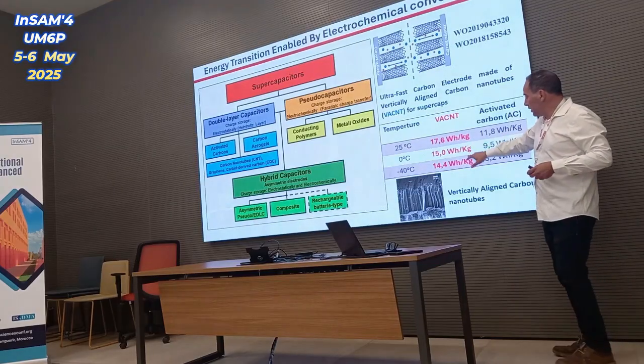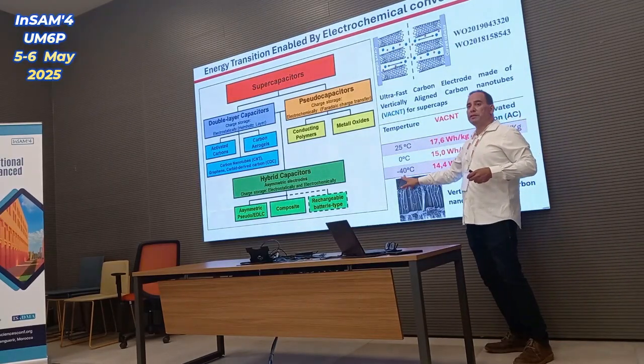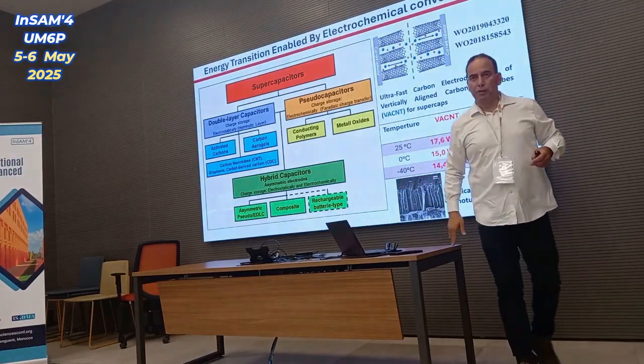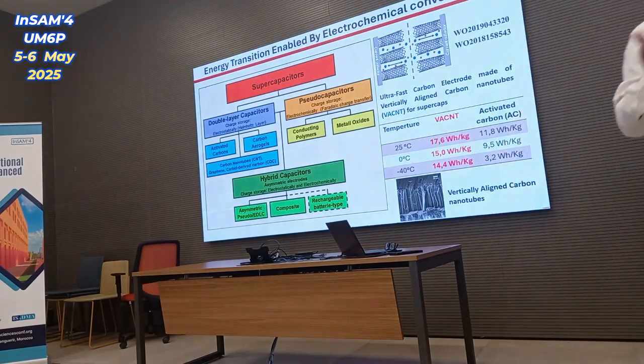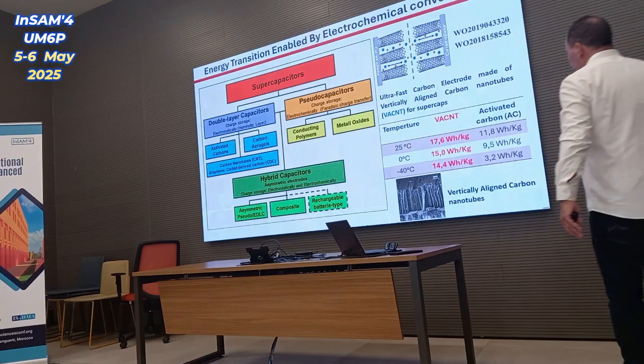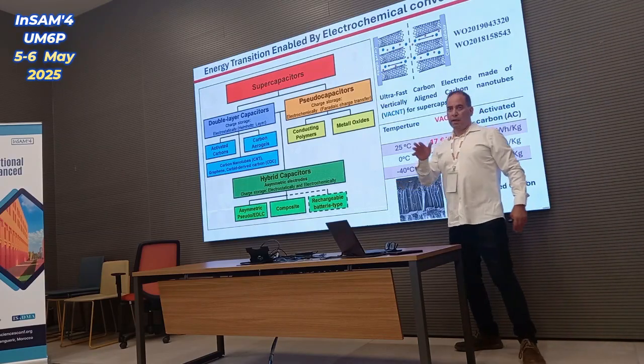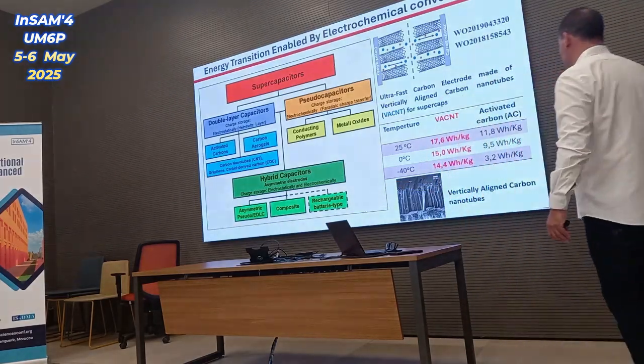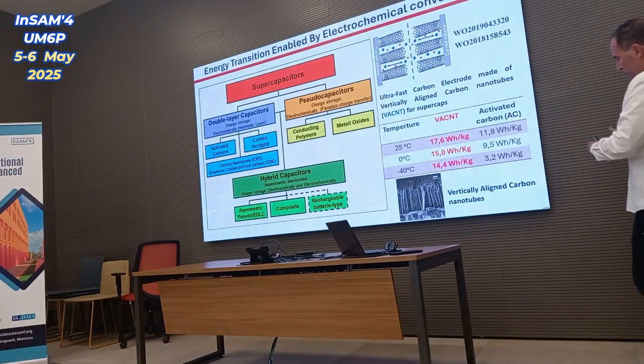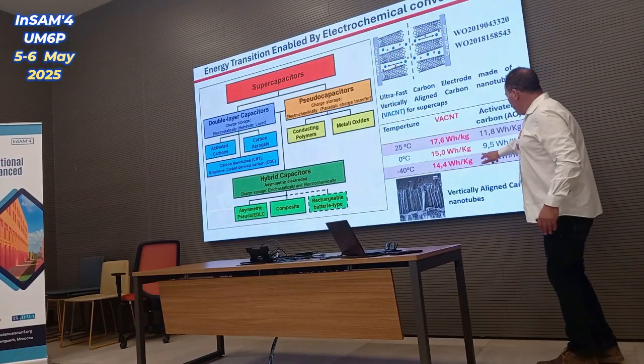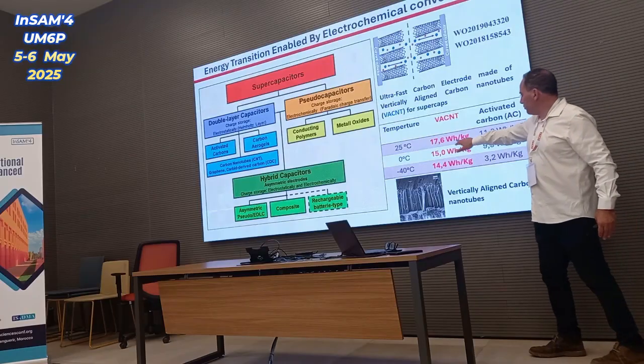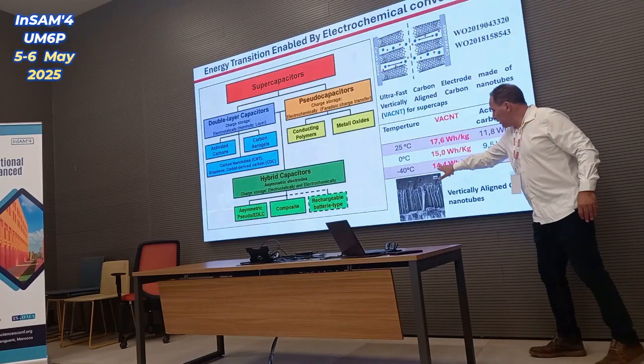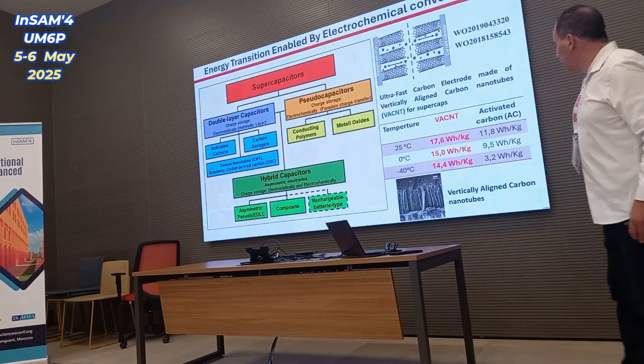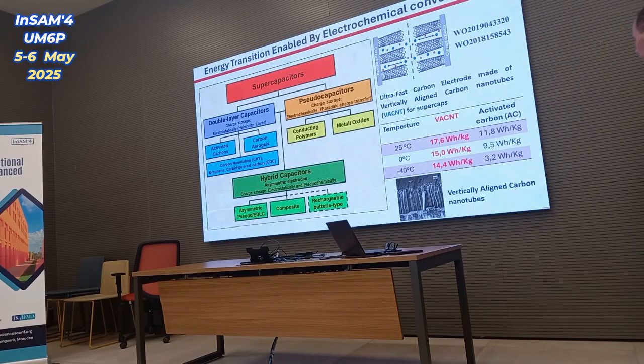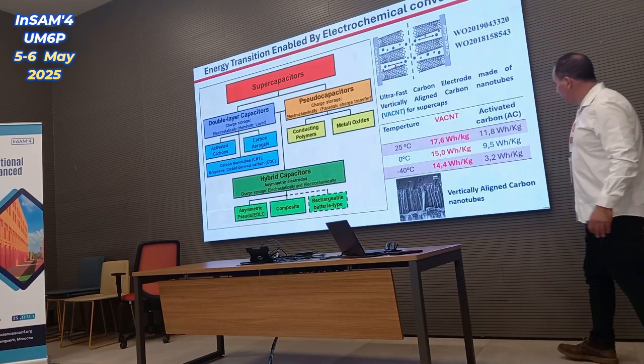This is the energy at different temperature, minus 40 degrees. This is an advantage of supercapacitor by comparison to batteries. Batteries at minus 50, minus 60, we stop the functioning. Supercapacitor can operate at minus 40 degrees. And the reason is the electrolyte. So using nanotube, we still keep decent performances even at minus 40 degrees by comparison to conventional activated carbon.